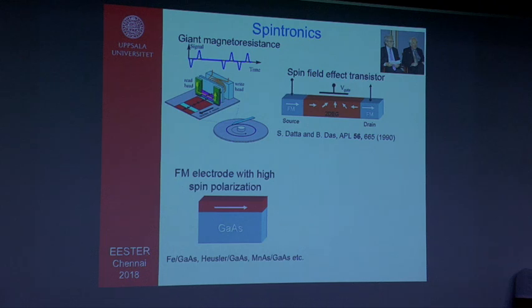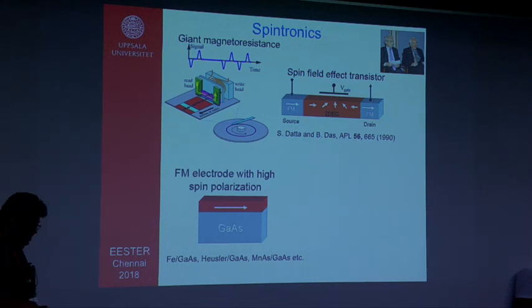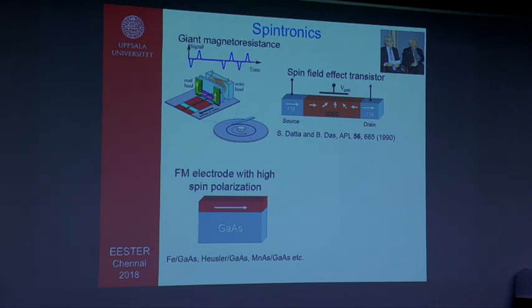The other thing is, of course, I have discussed a little bit, you need a ferromagnetic electrode with high spin polarization. You can think of a ferromagnetic metal like iron, where you want to inject some spins into gallium arsenide, a standard semiconductor, but immediately you see that there is a problem because this is a metal, this is a semiconductor. They have a huge resistance mismatch, and it will not work so efficiently.